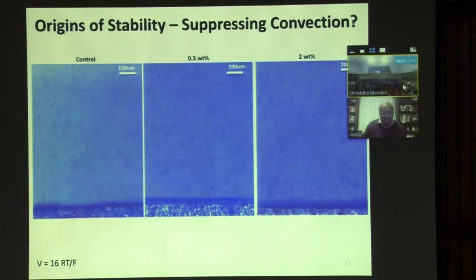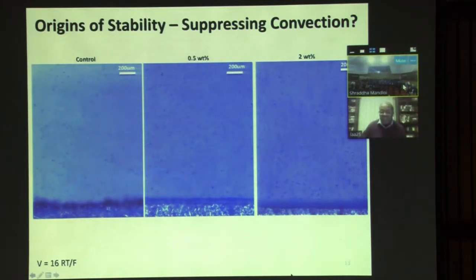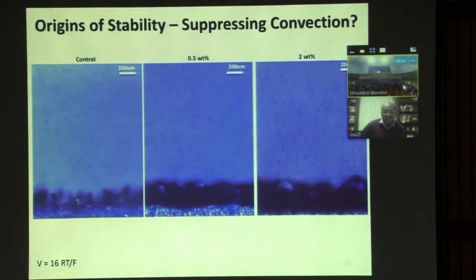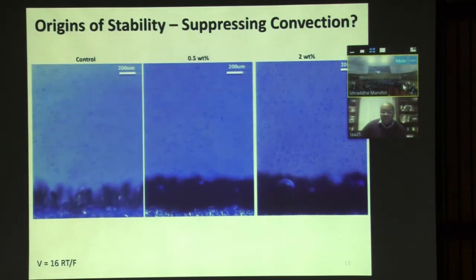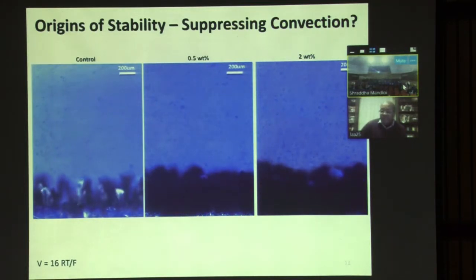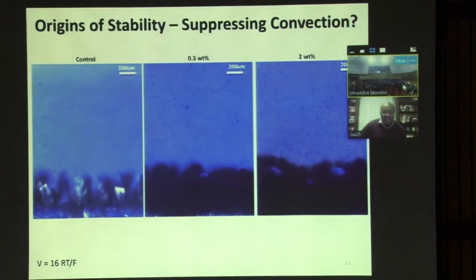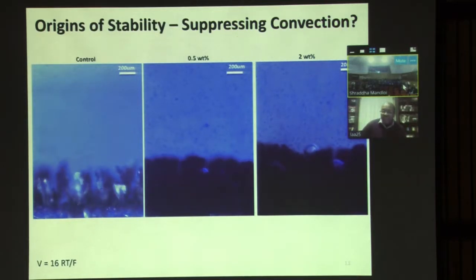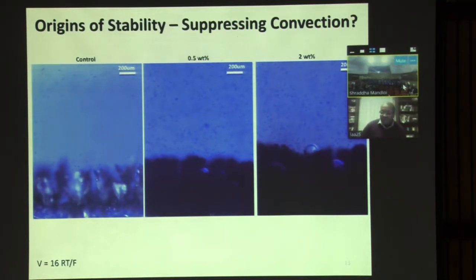Three videos show what happens as zinc is depositing at an interface: on the left, the control with no polymer; in the middle, 0.5 weight percent of 8 million molecular weight PEO in aqueous electrolyte; and on the right, 2 weight percent. It doesn't take much to see that the deposits are more uniform with the polymer and don't have the characteristic dendritic structure. This indicates the polymer is not just effective in suppressing the over-limiting conductance, but it's suppressing the phenotype of that conductance—which is the dendritic deposition.